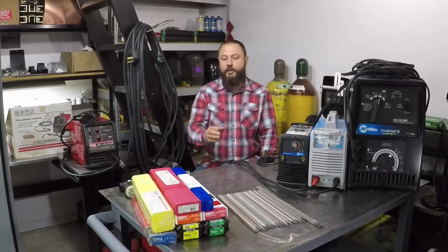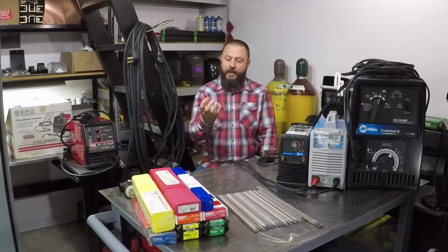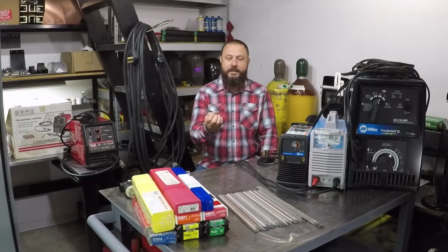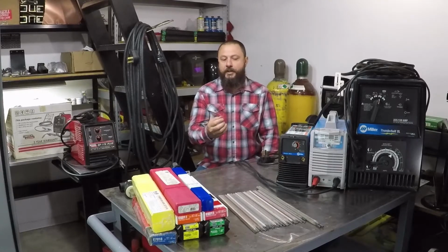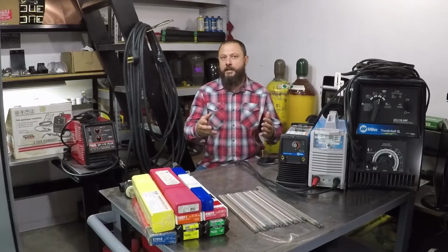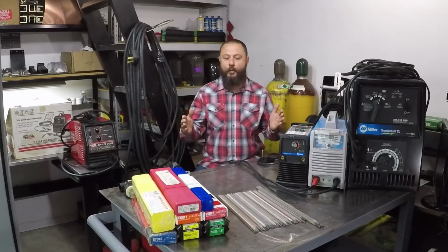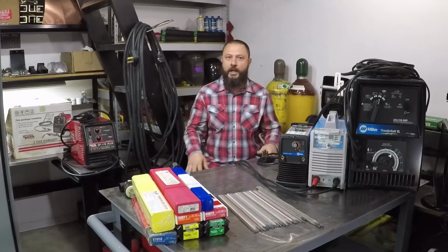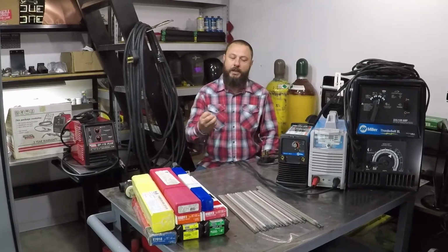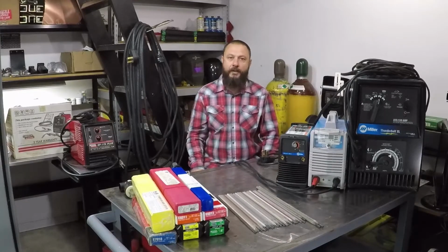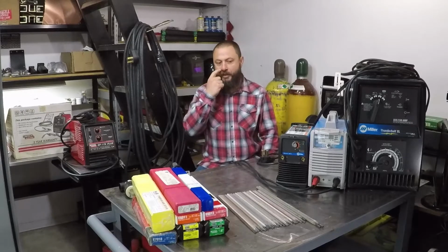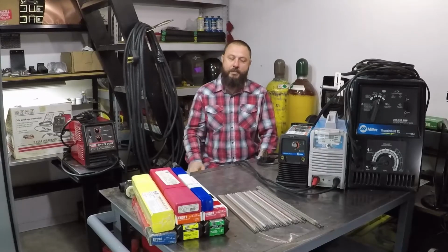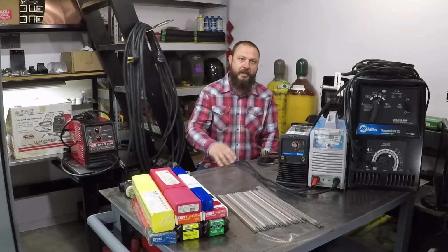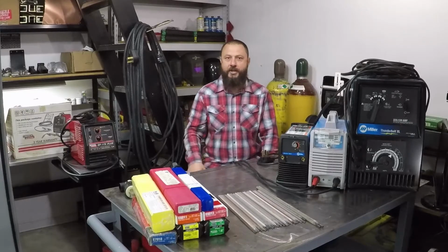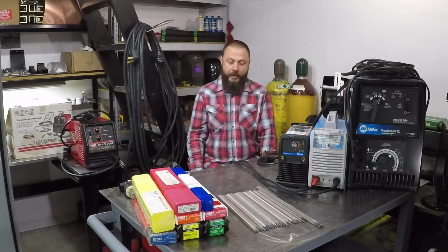This could happen because the rod is too old. In the case of 7018, if it has absorbed moisture, it's not going to be a good rod. They put them in the oven. There are special welding rod ovens to bake them to around 300 degrees, and this will let the moisture out of them. But sometimes if they sit for too long, they may not be good anymore, especially if you start seeing rust on them. Just throw them away and go buy new rods.